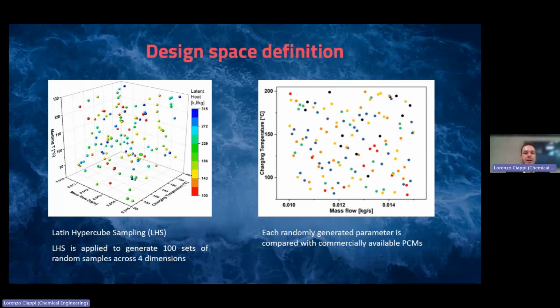For what concerns the PCM, the melting temperature and the latent heat were varied, while for the heat transfer fluid, the mass flow rate was considered in its variation, and different levels of charging temperature were considered. For each randomly generated parameter, the correspondence of the desired parameters with the commercially existing PCM was evaluated.